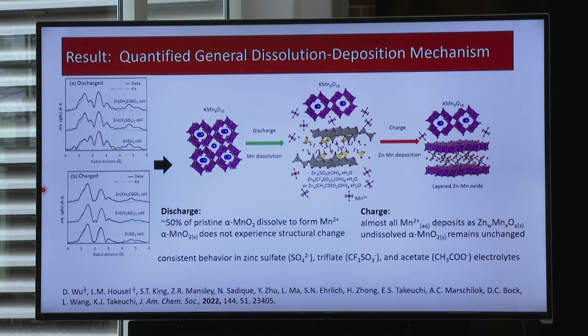We tested this mechanism in a series of electrolytes using sulfate, acetate, triflate, and this general mechanism holds true independent of the anion that's present. The anions lead to different levels of cell efficiency, but generally the mechanisms were pretty universal across these different electrolyte systems.